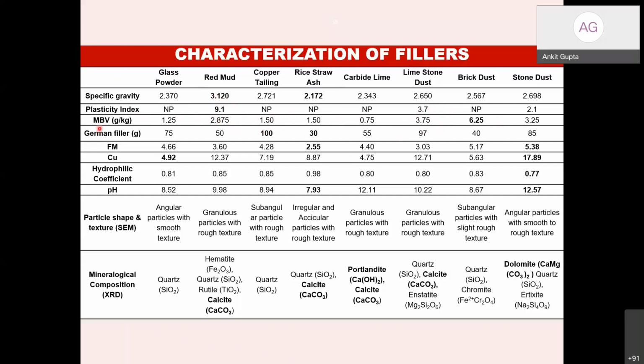The methylene blue value, well, this is not an indicator which is there in the Indian codal guidelines, but it is there in the European guidelines. It is basically a test for finding out the organic impurities present in the fillers. So most of the values are more than 1 except this carbide lime, so that does not have any organic impurities present in the fillers.